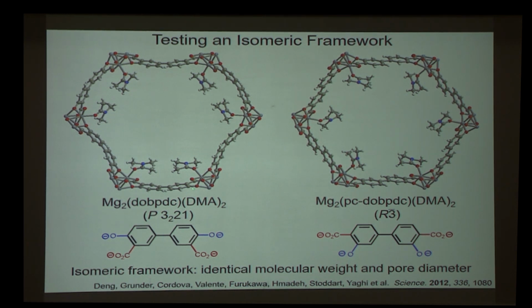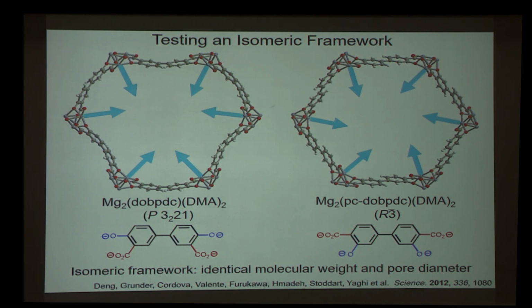Shown here is the framework I've been showing all along, and this is the organic linker that we used to build it. It has phenoxides in opposing para positions. The linker used to assemble the isomeric framework is very similar, except it has carboxylates in opposing para positions. And what you'll notice is that the isomeric framework has some very similar properties. It has the same molecular weight and an identical pore diameter, but there is a subtle difference in the geometry. It may be hard to see from these structures where solvent molecules are bound to the metal sites, but these arrows should help you to see it.